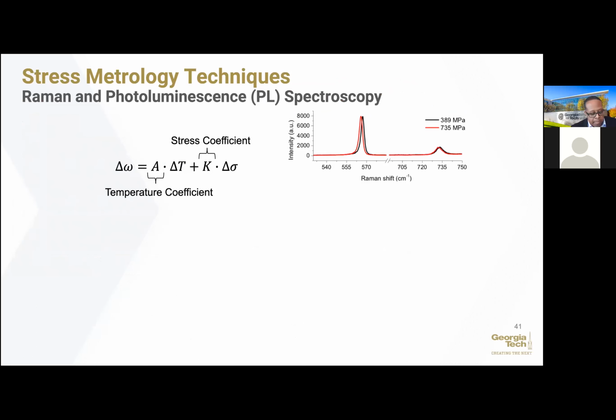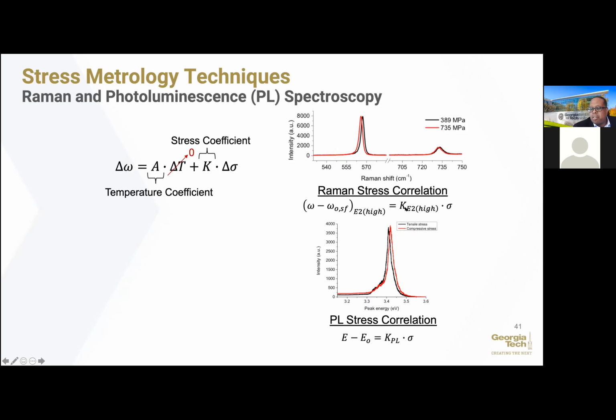So another thing that comes up, if you go back to what I said about the GaN on silicon, we were worried about stresses. So here, we're also going to worry about stresses with the diamond. So we're going to use a couple techniques. Number one, we're going to use Raman spectroscopy. And I showed you before, I can get these two gallium nitride peaks. And these peaks will move with both temperature and stress. So when I do this measurement with Raman spectroscopy on these materials, I'm going to do this at room temperature. So any shift in the peak has to come from the stress component as well. So we'll see a shift in the frequency of the phonon peak that is linearly related to the stress in the film. And so we've gone through and we figured out these correlation factors, the K here.